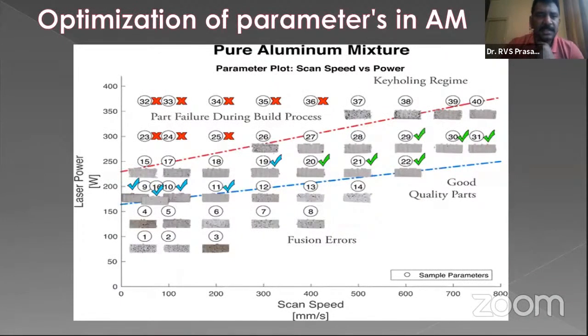So for example, in this case, it's a pure aluminum mixture. People have done a number of experiments. You can see more than 40 experiments. However, the green color images are the optimized process parameters with a particular laser power and scan speed, where you are able to end up with good parameters. But out of this, you have to check which gives the best mechanical properties, with better ductility and heat treatment optimization. Then you can end up selecting those locations and freezing the process parameters.